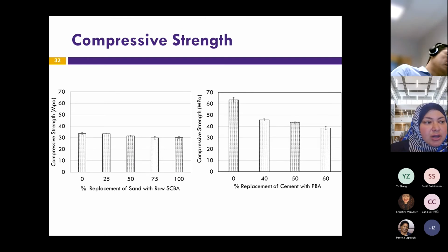This is just a snapshot again of results. So the compressive strength, as you can see from these figures, the use of sugarcane bagasse ash as sand replacement produced minimal effect on the compressive strength. It works pretty well there, but it did reduce the compressive strength when we used it as cement replacement.